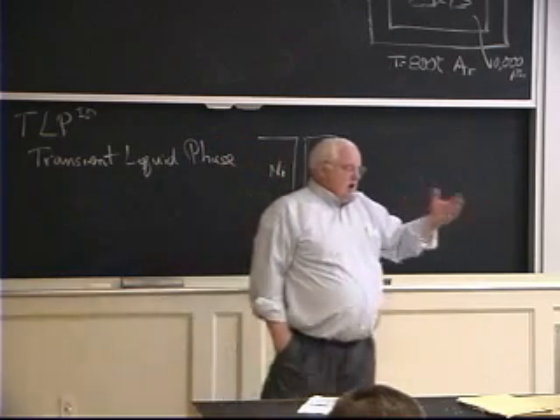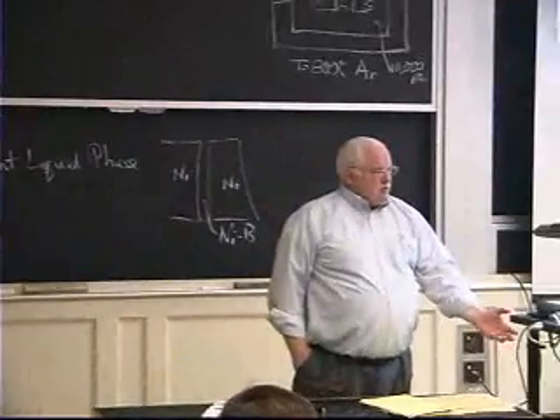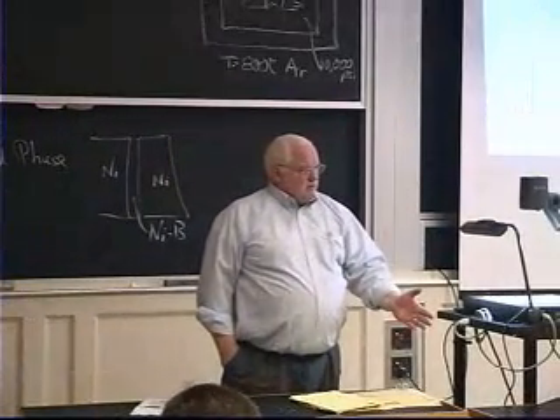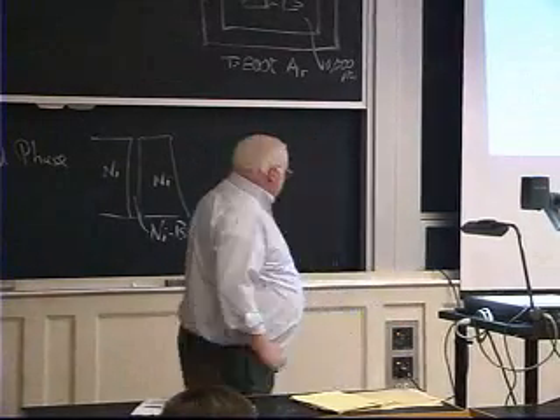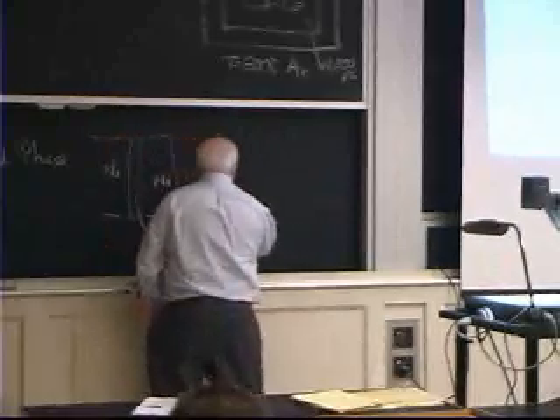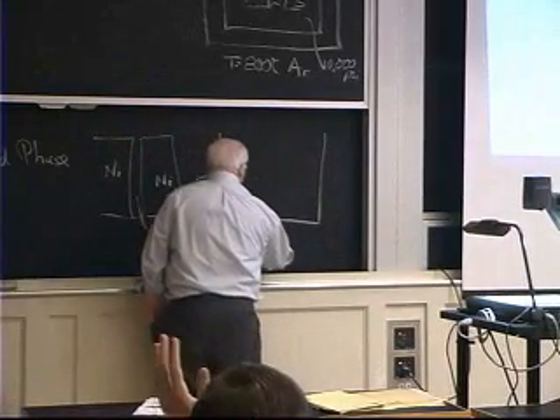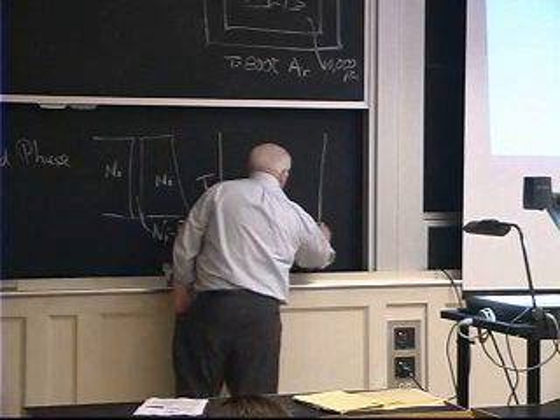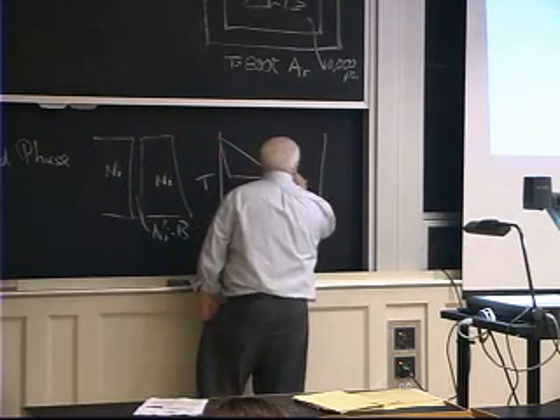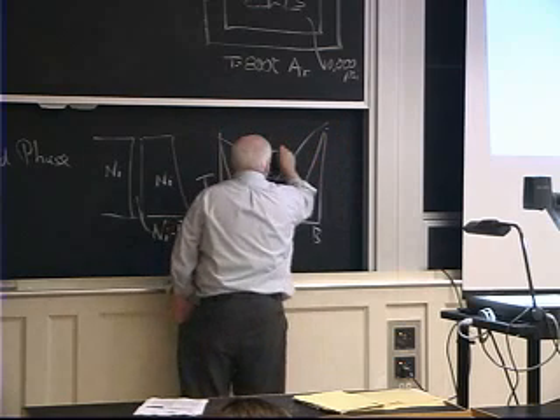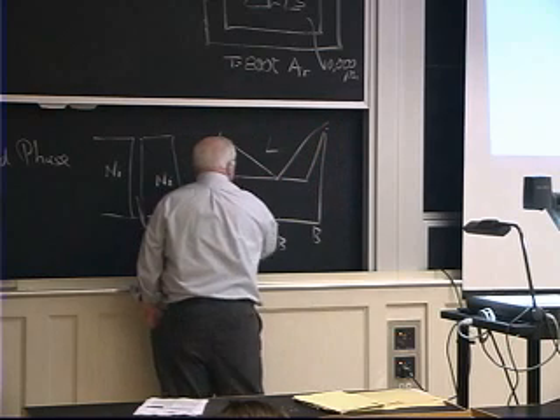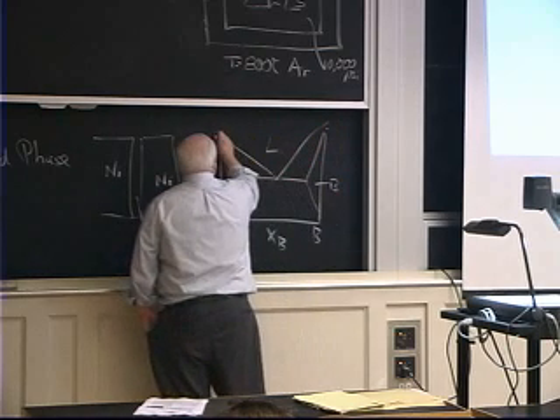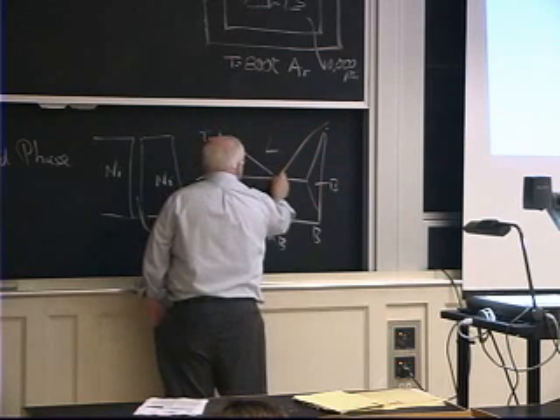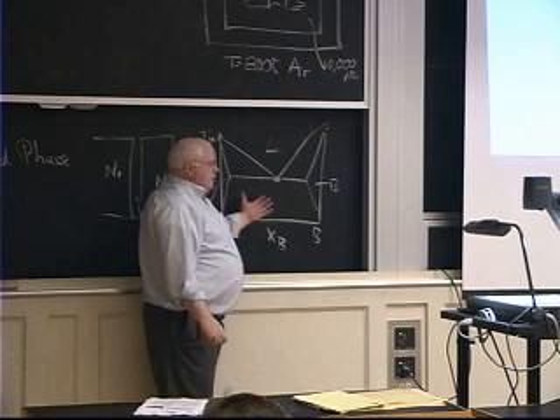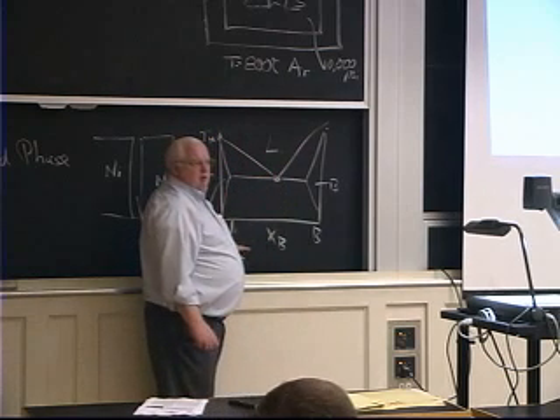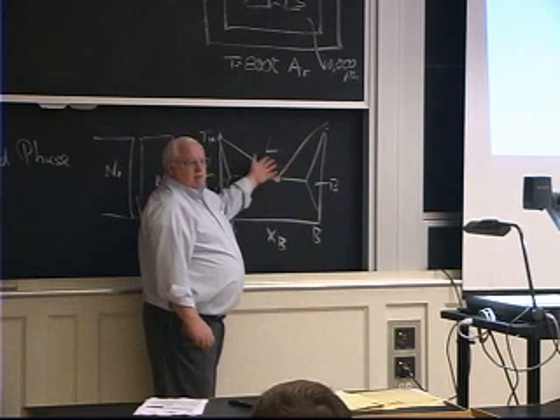Now, we know solidification right now. I take a liquid and I cool it down. As I drop the temperature, this is called athermal solidification. I drop the temperature, it solidifies. But I can also go across the two-phase phase diagram, and how many of you even know what a phase diagram is? Temperature versus composition. If this is nickel and boron, it turns out the nickel-boron phase diagram might look something like this. Boron goes way up. But I have liquid, I have solid nickel with a little bit of boron, and over here I might have solid boron. This is the melting point of nickel, pure nickel. This is the melting point of the alloy. This is the braze alloy. It's lower. This type of phase diagram basically shows on a temperature composition map between nickel and boron how I lower the melting point by adding another thing to it.